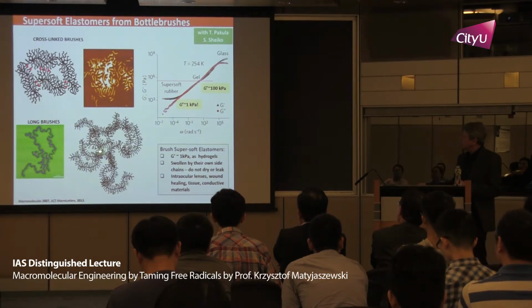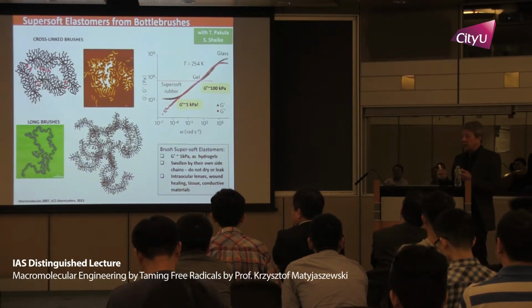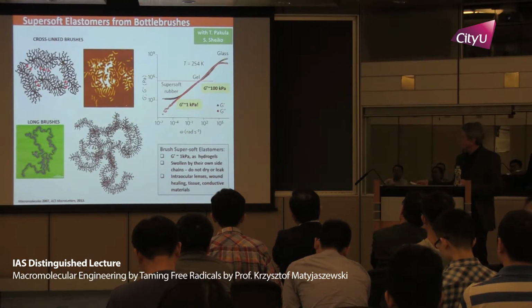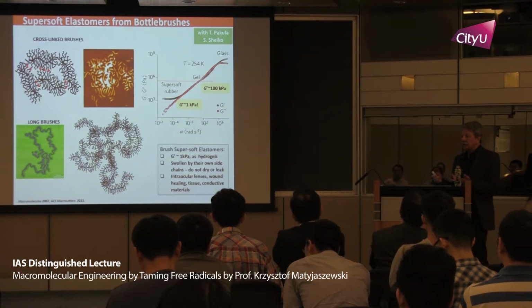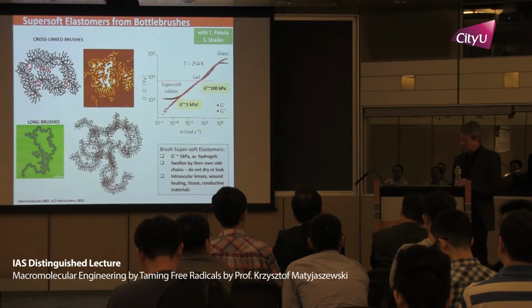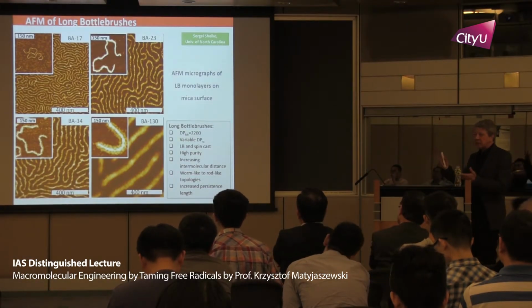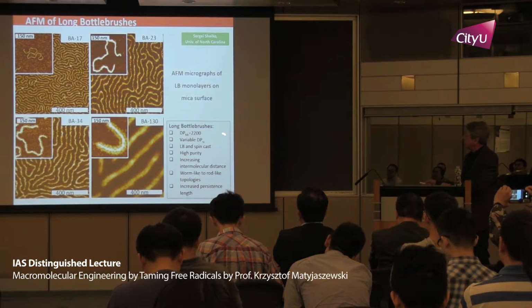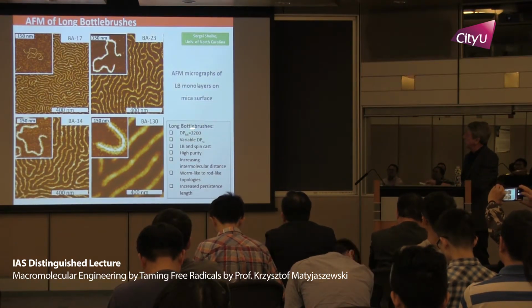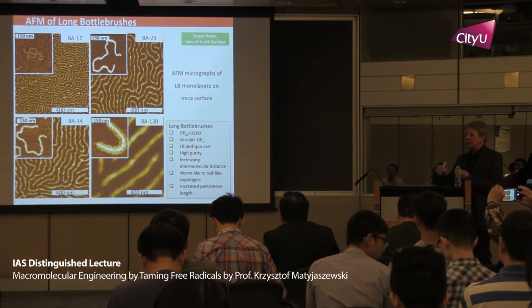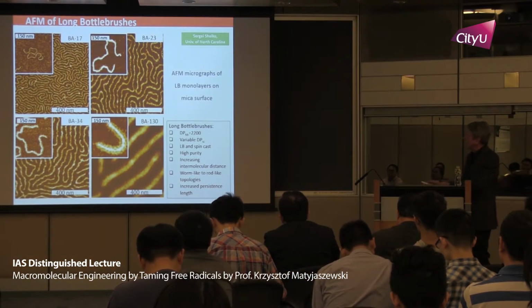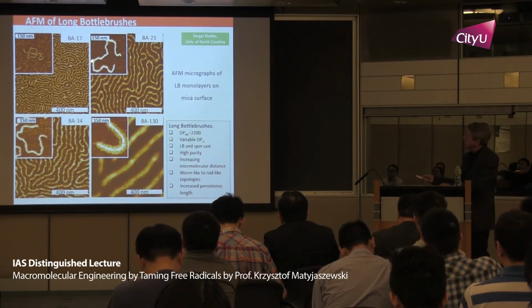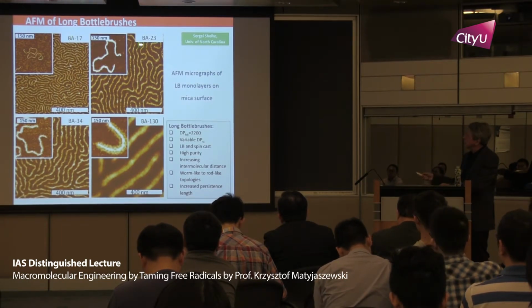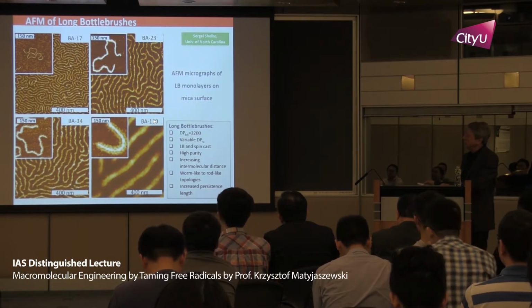So we start with a network, which is really like a hydrogel, but we swell it in monomer and grow these short side chains. They cannot entangle, and in that case, they act as a diluent, which would never dry because these short side chains are connected permanently. So here is really an example of how we do it. We start with a bottle brush backbone, degree of polymerization 2000, so they are roughly speaking half a micron long, sometimes up to a micron. And then we grow side chains from degree of polymerization 17, 23, 34 to 130.